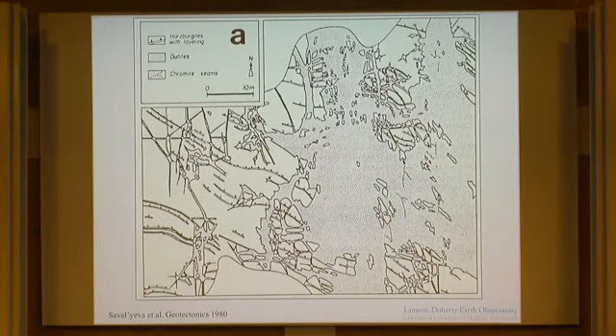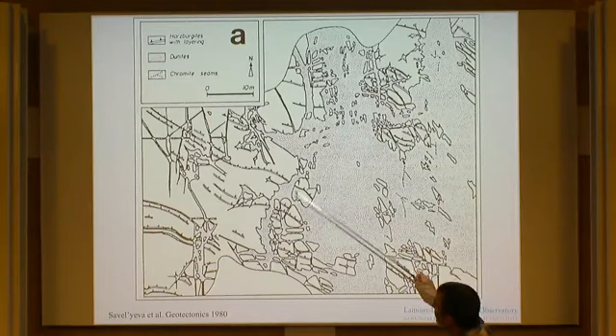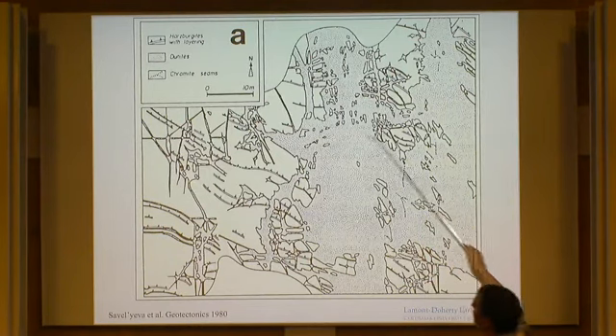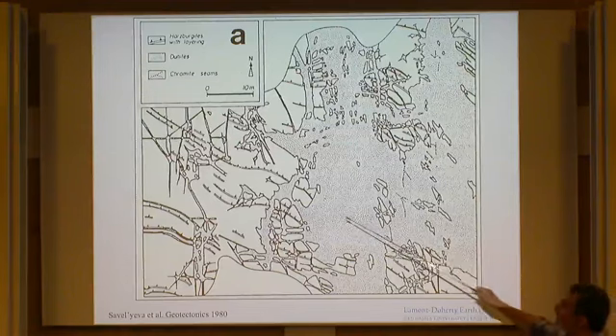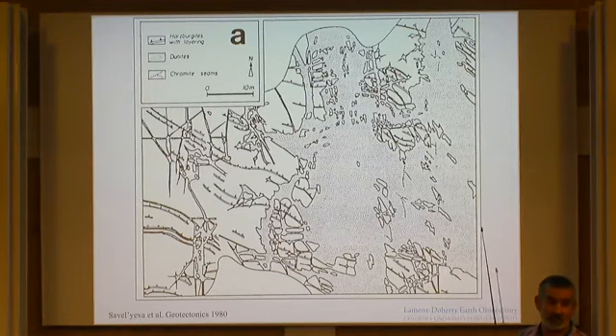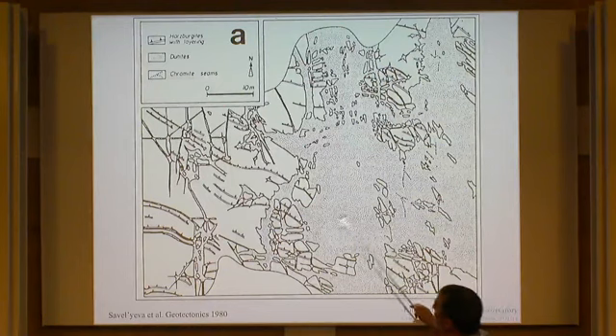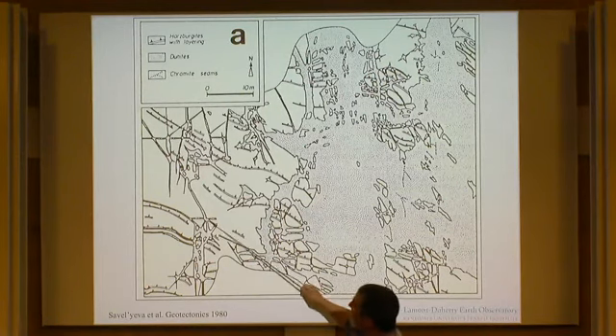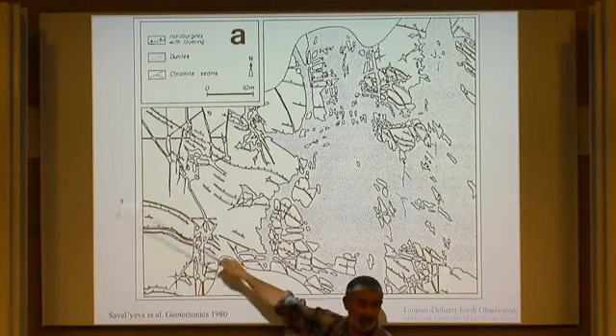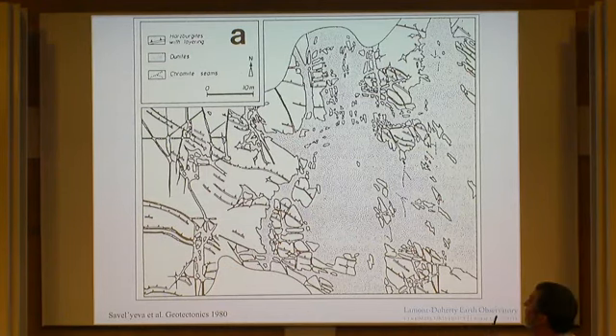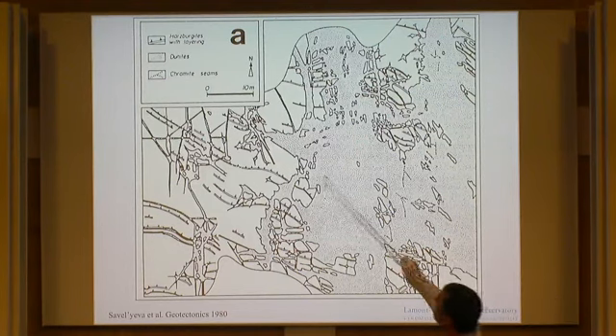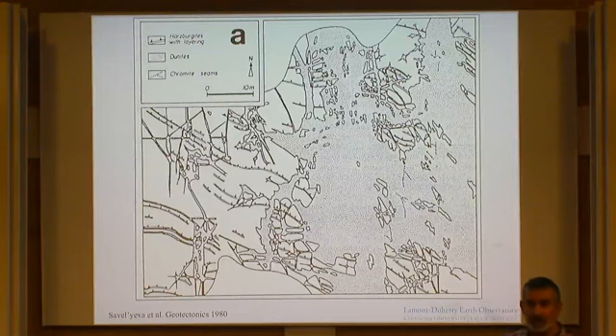And here's a map from the polar Urals that's much more beautiful than mine. You can see a lot of different features in this. You can see that there are blocks of relict peridotite left out in this big sea of spotted dunite, but they're not rotated with respect to the wall rocks. You can see in places that the dunites have preferentially replaced pyroxene-rich bands in the peridotite. What else? You can see that where the dunites cross material lines at an angle, there's no dilation or contraction that you can really measure.